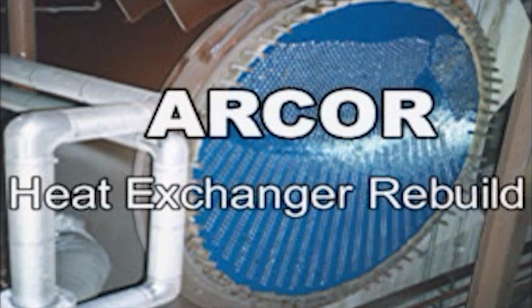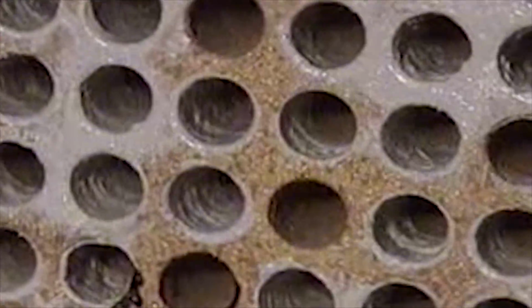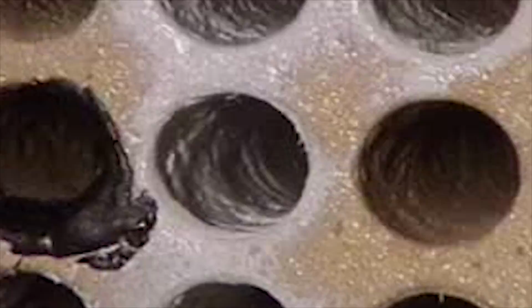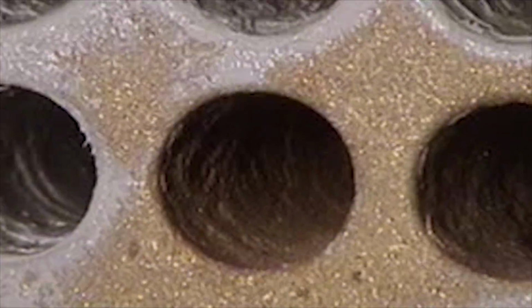This is an epoxy repair of a damaged heat exchanger exhibiting severe inlet end erosion. Here's the tube sheet after blasting with a fine Black Beauty 20/40. Subsequent blast with a medium 12/40 grit to get the profile you see.